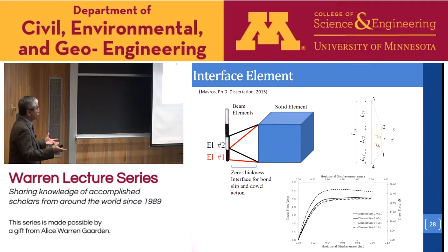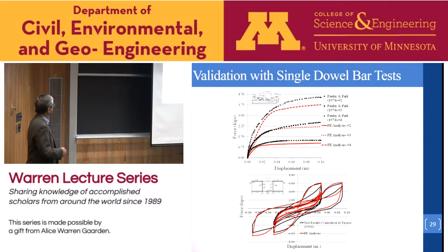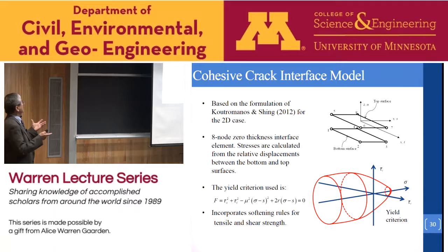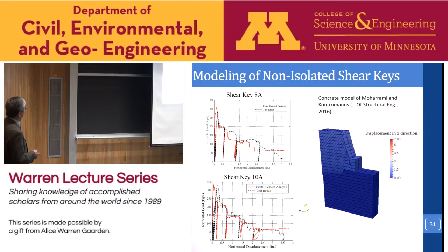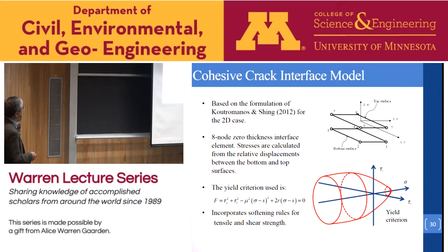So we validated this model with a lot of test data, like monotonic dowel bar tests and also cyclic tests. And then we also implemented a cohesive interface surface to model the sliding of the shear key, through the construction joint or also through a cracked interface. So this model is actually an extension of a 2D model developed previously by my student and myself. So now we expand this to a zero thickness 3D interface.